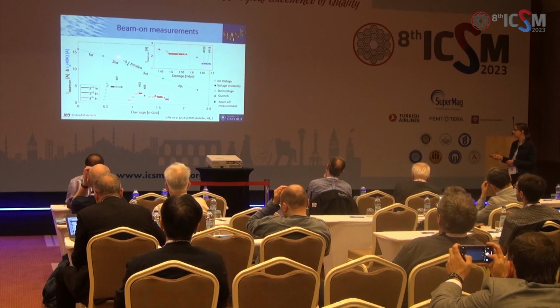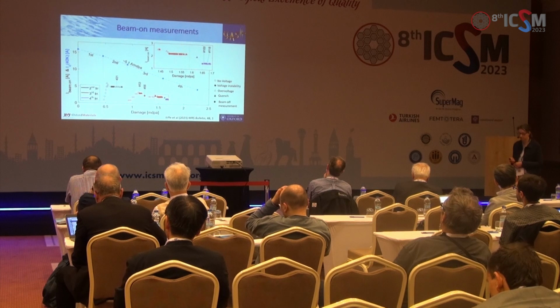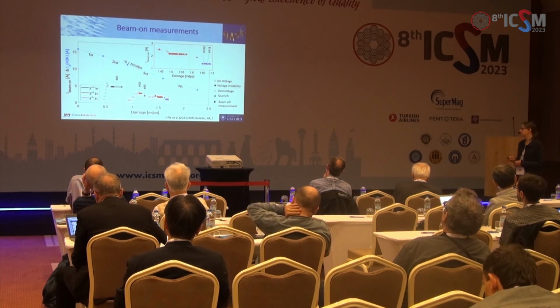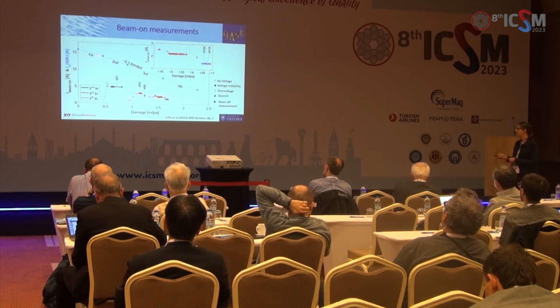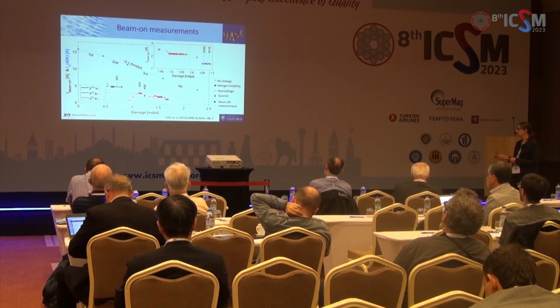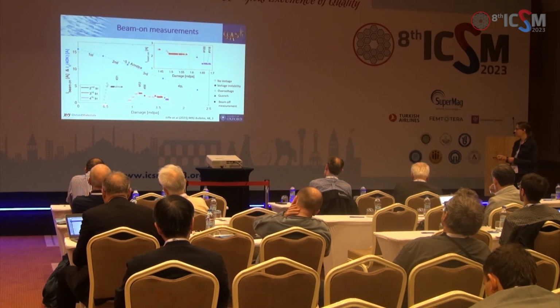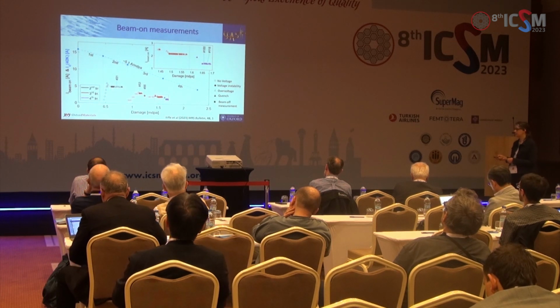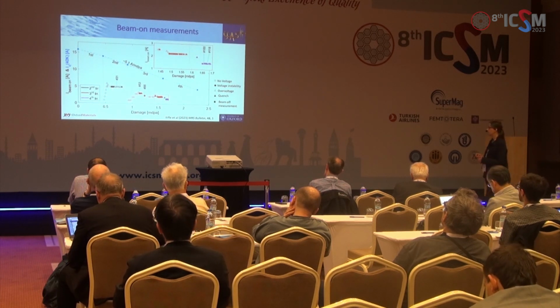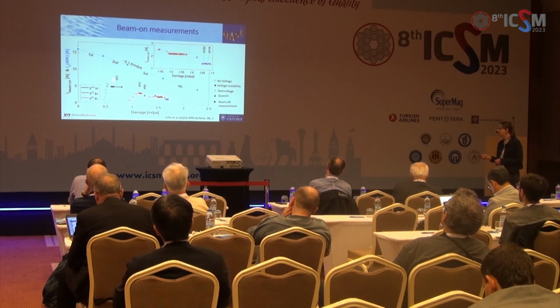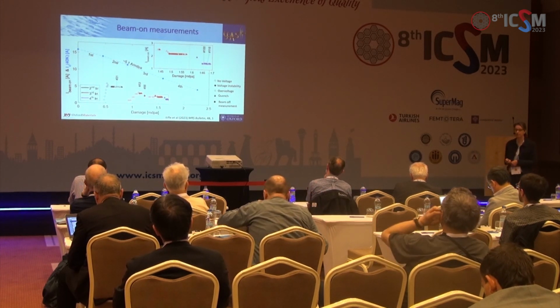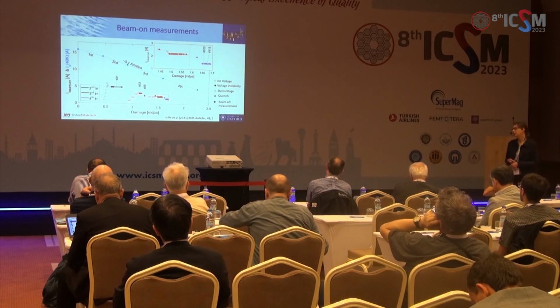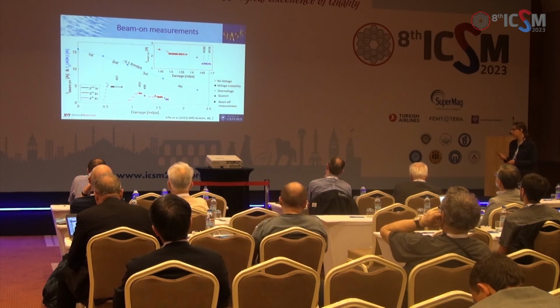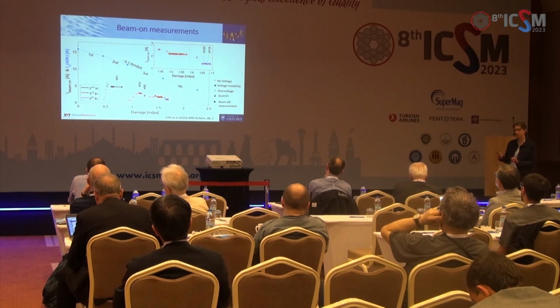So here is the series of experiments we did with the beam off. So we turned the beam off and measured. And after the first time we did that, we started measuring during with the beam on. And here's our increasing current. We see a voltage when we back off. So that's that measurement I told you we were going to do. But what you might notice is that we're nowhere near the current that we could get with the beam off. When the beam's on, we're about a third of the current that we can get with the beam off before we start seeing this voltage.